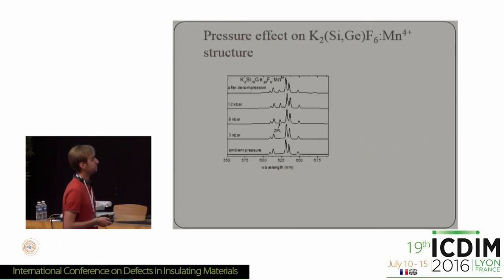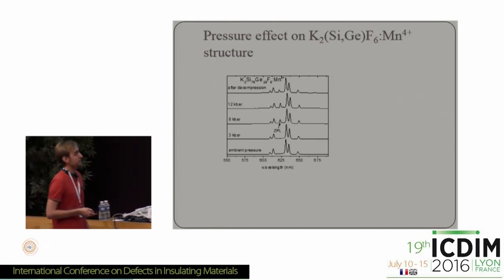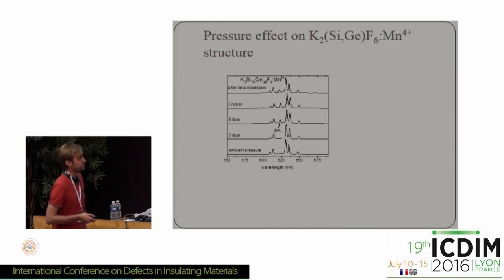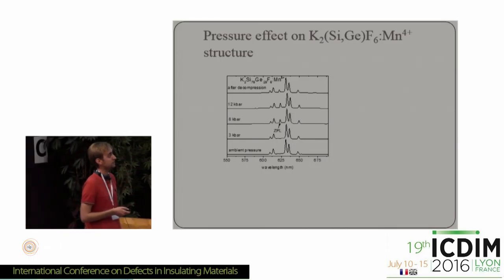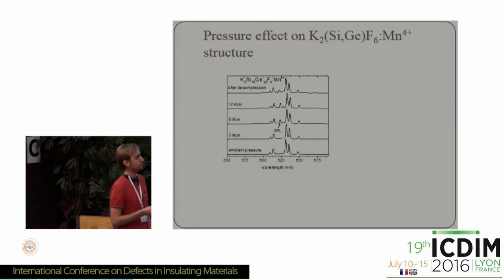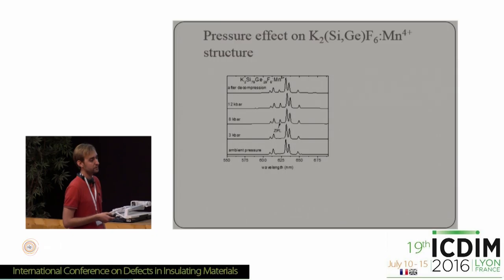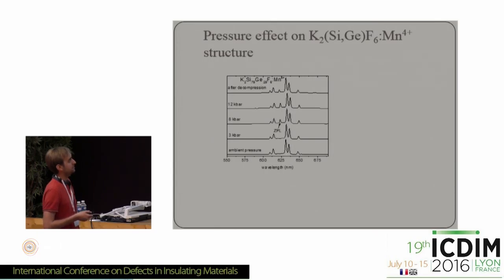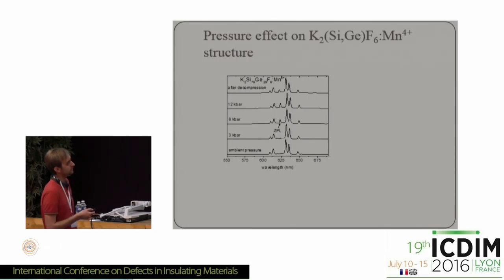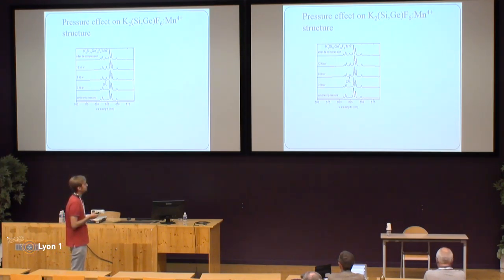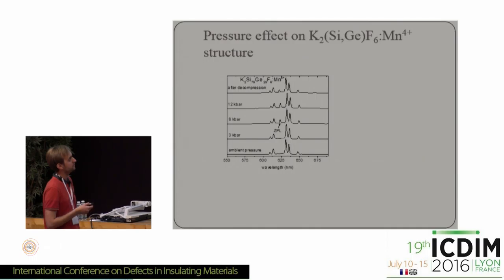We also tried to find evidence of phase transitions in the KSGF mixed crystals by means of optical spectroscopy, looking for changes in optical spectra after applying pressure. In a representative example, we have a silicon-rich mixed crystal where at a certain pressure — 8 kilobars — we see that a zero phonon line appears, indicating some sort of crystal structure change. This change is permanent: the emission spectrum after decompression still shows the zero phonon line.